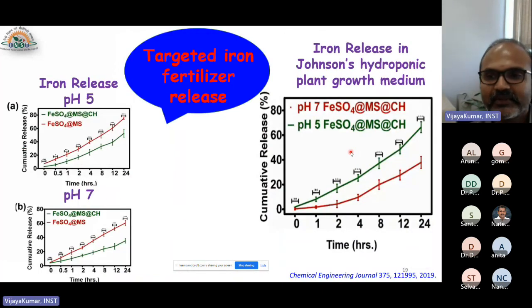Now we have to show that it is showing a targeted release. So we check the release kinetics with pH 5 and pH 7, and we were able to see that at pH 5 there is more release, and when it is coated with chitosan, it is showing controlled release when compared to uncoated silica material. And the same has been demonstrated with the growth medium. In the growth medium as well, pH 5 is showing an increased release, which shows that there is a targeted release happening compared to pH 7. So when the root is nearby, at around acidic protonation of the root zone, it will be releasing more.